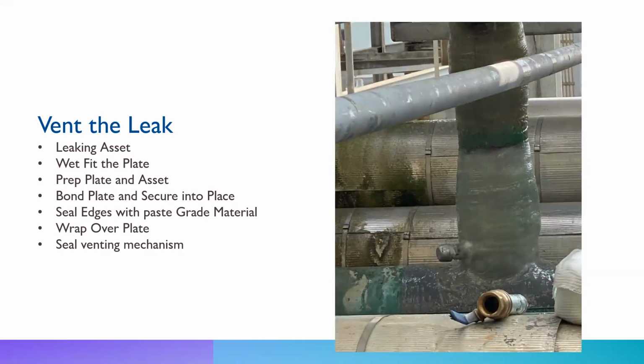So this is basically a solution when you're dealing with a high flow scenario, tough access area, but you do have to have that way of diverting the flow during the application because you can't just have it dripping on you as you're doing it. So you do have to have some way of collecting everything and have to realize that once you install all these things, you have to allow them to cure before you can cap off the vent. So we do have some products that can cure in 2 to 4 hours. So that's typically what we try to use to have the least amount of venting time so that we can stop the leak as fast as possible.